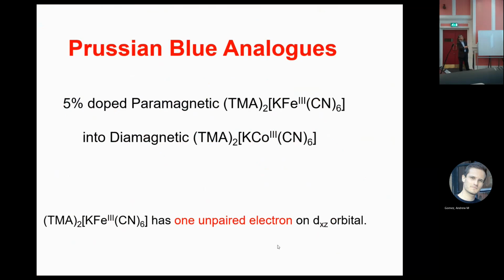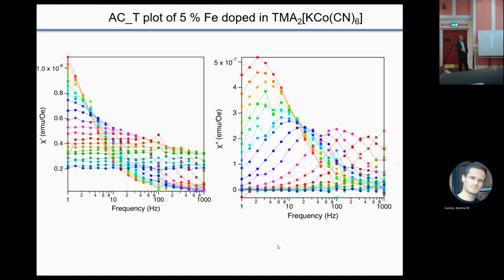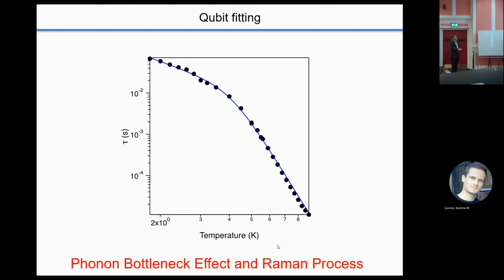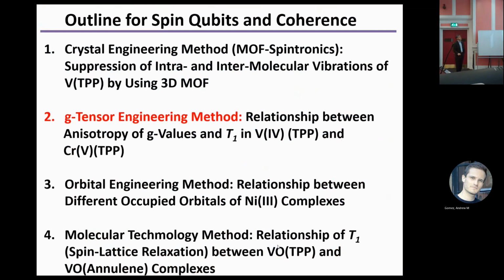So then we switch to the Prussian blue analog. So hexacyano cobalt 3 is a low-spin diamagnet, but iron 3 is a paramagnet. So iron 3 has one unpaired electron in the dxz orbital. I dope iron into the diamagnetic cobalt. So a very beautiful frequency difference is observed. One iron atom shows a slow magnetic relaxation. One spin shows a slow magnetic relaxation. This is available for a molecular spin qubit, and the relaxation mechanism is the phonon bottleneck effect and the Raman process. So let's move to the g-tensor engineering method.